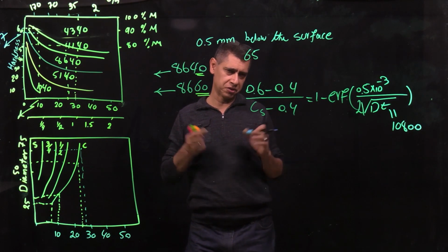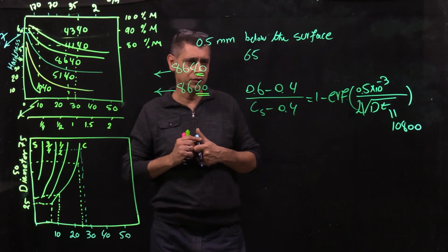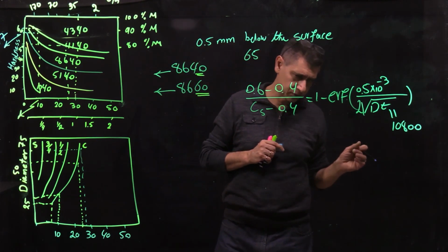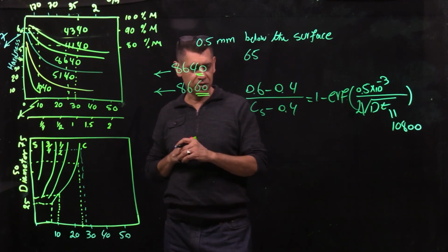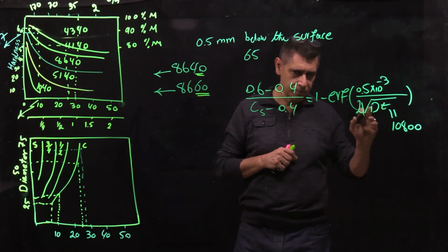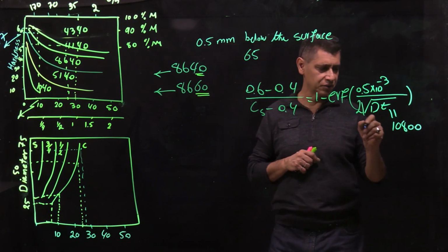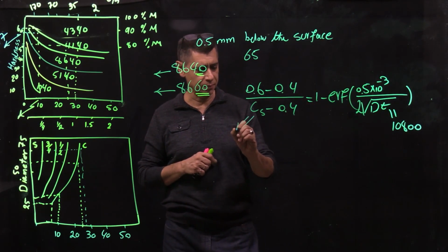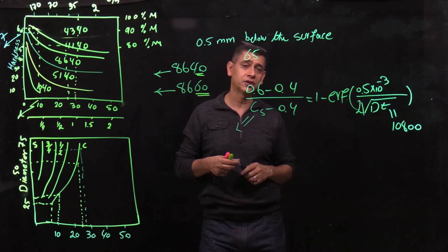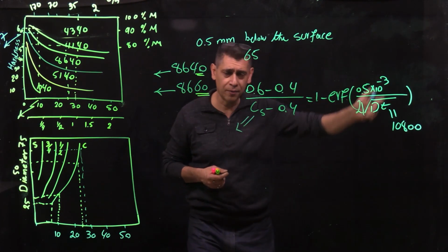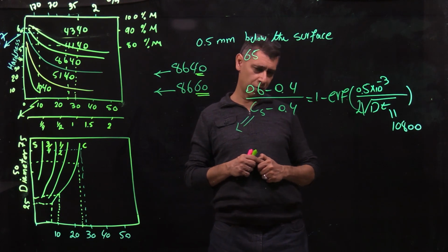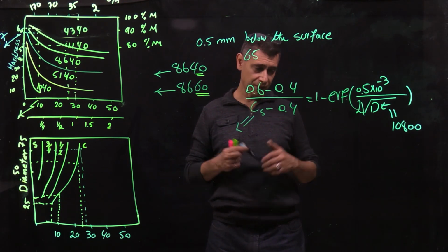In this case, obviously, you are talking about the diffusion of carbon in austenite. So D sub naught is given, Q_A is given, you calculate this D at the temperature, so you have this. Everything is given, you calculate this C sub s, which is the carbon content of the gas, and from there you simply calculate the required pressure. That's one way.